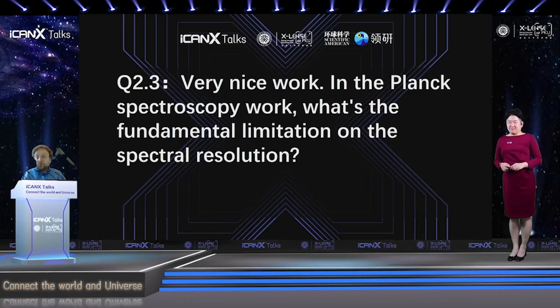I think the best way to do better and not run into this very poor scaling is to do the measurements with a bunch of different degrees of freedom. Instead of just one direction, maybe you tilt the angle a few times and do ellipsometry-type measurements, or you change the polarization. You want to try to get extra information, and then the computational algorithm will be able to do better. So I know that's not exactly the answer to your question, but that's the flavor of where we are.